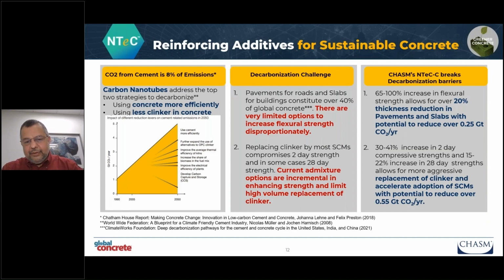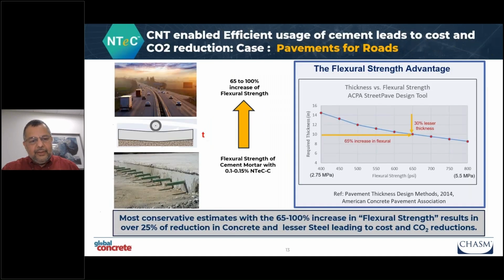It improves ductility, no doubt. The strength is a little different perspective. And that too, to get a 40-70% increase or a disproportionate increase, nanotube seems to be one of the ways, and I'm open for more collaborations on this. And then clinker reduction, we already spoke about. And if well adopted, this can be almost 0.8 gigatons between the two approaches globally.